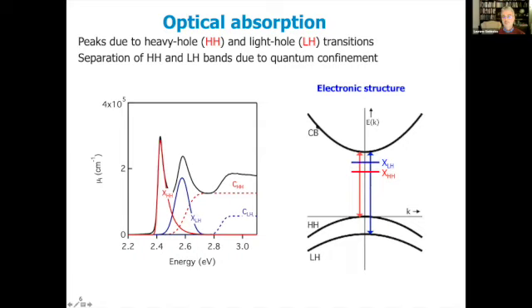Now, in the bulk, you have a conduction band, and you have a heavy hole band and a light hole band. And now you can excite an electron from the heavy hole band to a heavy hole exciton, and that gives rise to this first sharp peak. But you could also excite an electron from the light hole band, which is lying a little bit deeper, to produce an exciton, and that's giving this light hole exciton peak. And then there are continua where you directly excite an electron from the valence band to the conduction band, and